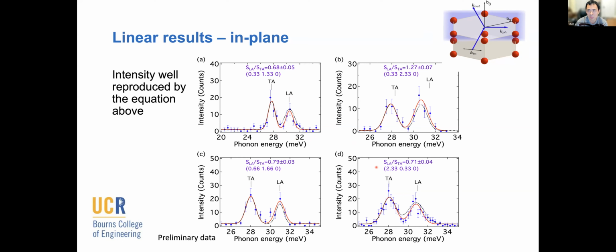But with further looking, what we realized is we are performing a scattering experiment in this in-plane geometry, which means our scattering plane here is in the basal plane of the hexagonal lattice of the tungsten carbide. What happens here is, in this case, both TA and LA angular momentum are going to be aligned perpendicular to the polarization of the X-rays, because the X-ray is horizontally polarized, and we have a 90 degree difference between the two. So maybe that's what's driving this